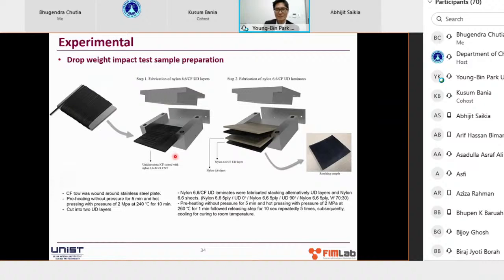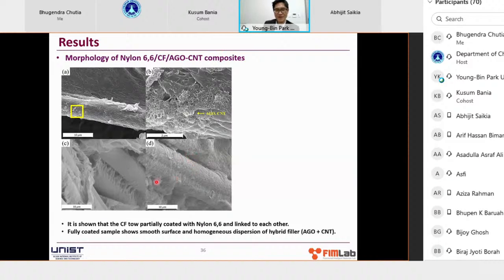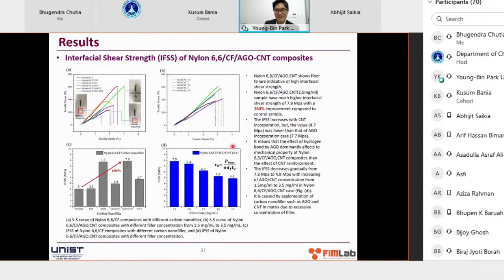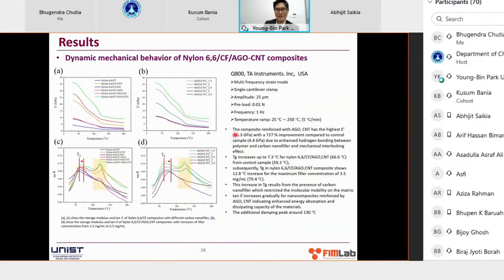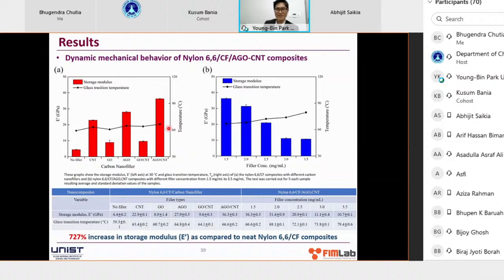I'm going to quickly go through. And you can see very, very good bonding between the resin and the fiber. Typically if you have poor bonding, you'll see a smooth surface of the fiber, but here you see a very nice coating. And then ultimately, we got really nice improvements in terms of the interfacial shear strength, tensile strength, and tensile modulus, and so on. And then also in terms of the dynamic mechanical behavior, we got good results. And these are the results.